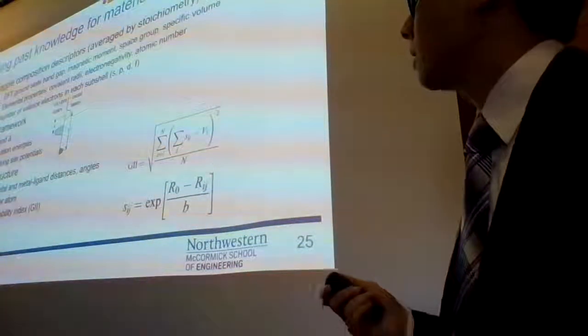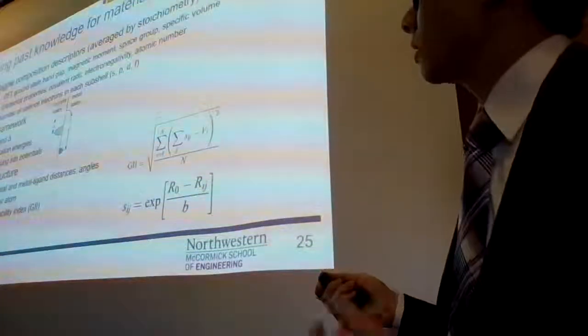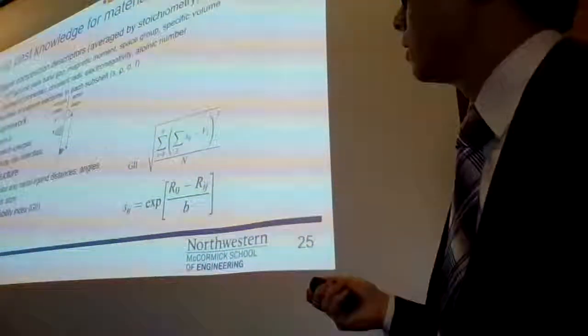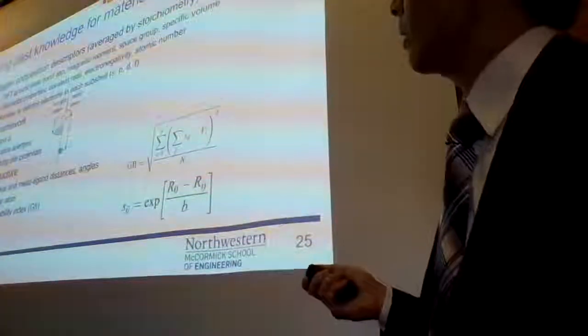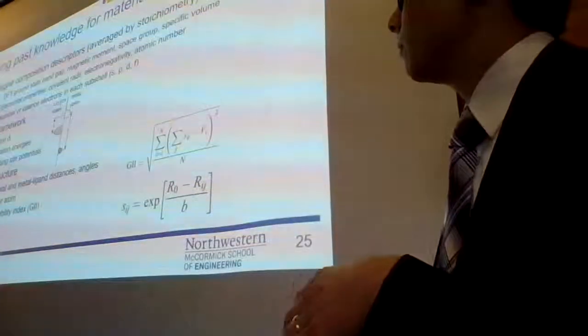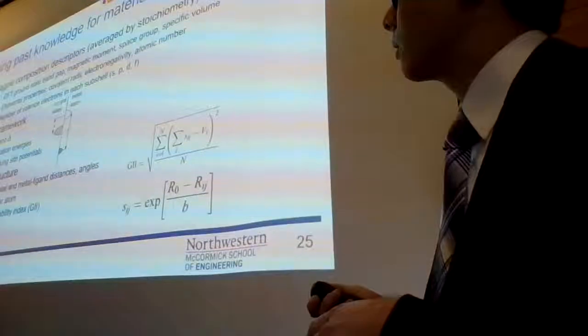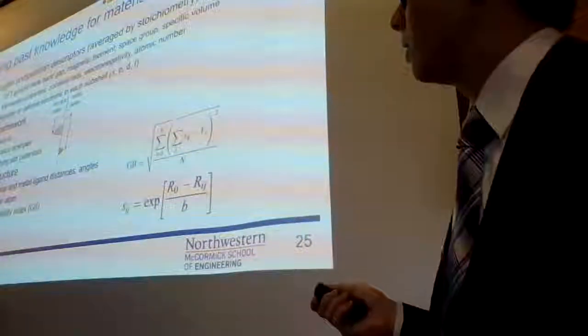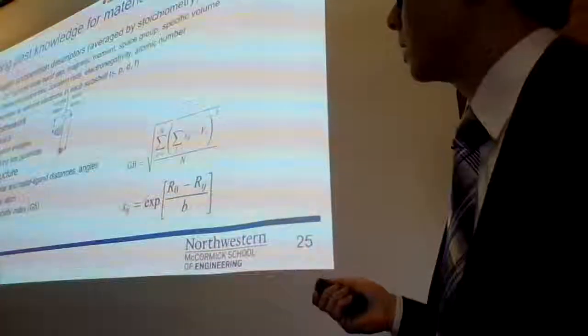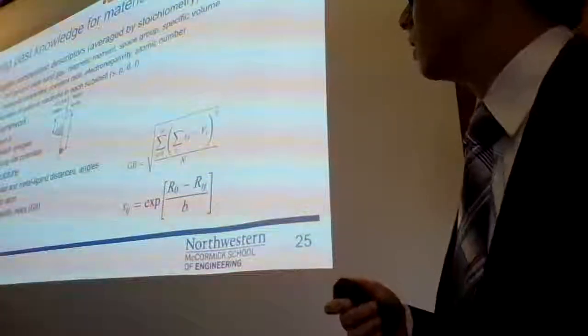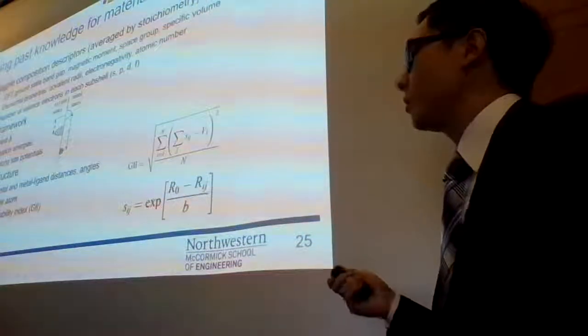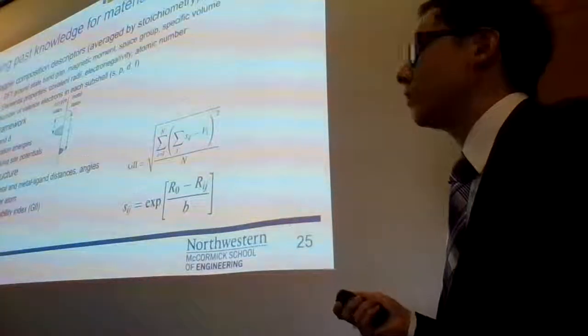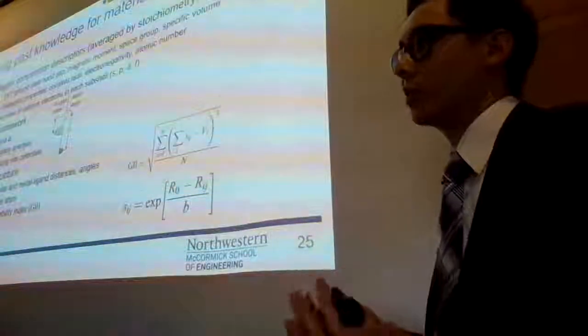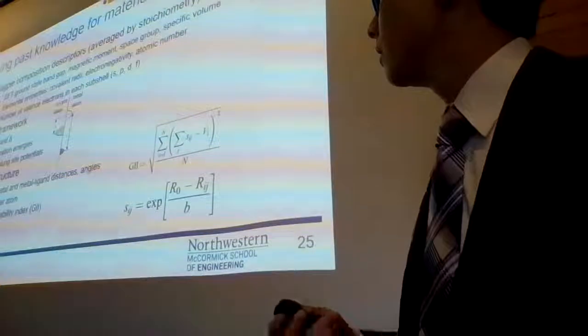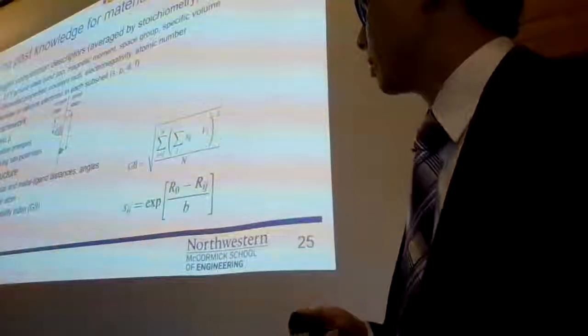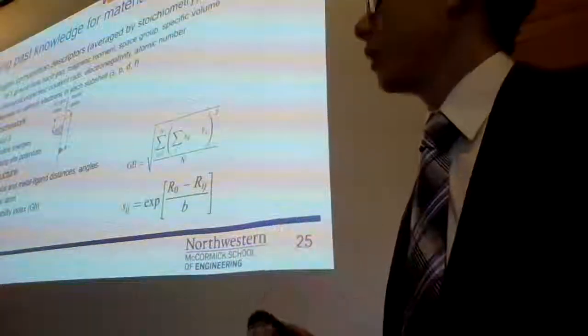in terms of properties. I also take some descriptors from the Zaanen-Sawatzky-Allen framework I mentioned before, so that U prime and delta parameter, I use those 2 features in my data set as well as ionization energies, which are used to compute them, and the Madelung site potentials as well. These are more hand-tuned features because they don't necessarily apply universally across the periodic table, but primarily to oxides. And then I also have crystal structural information because the structure is so vital to understanding the metal insulator